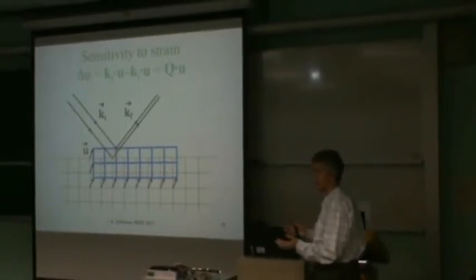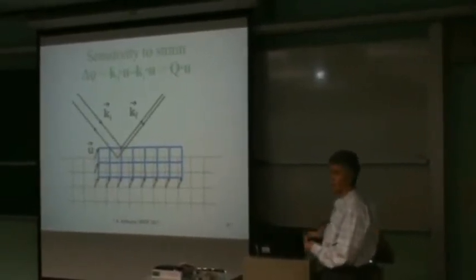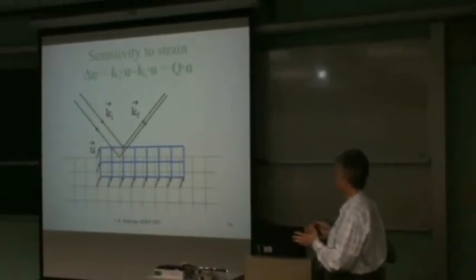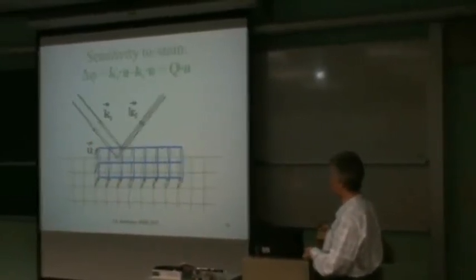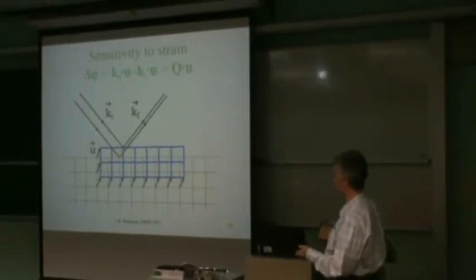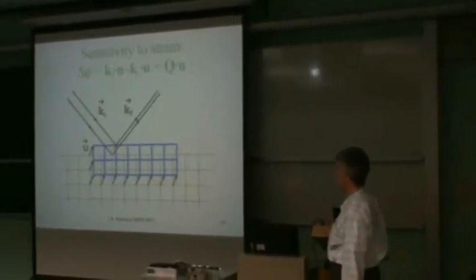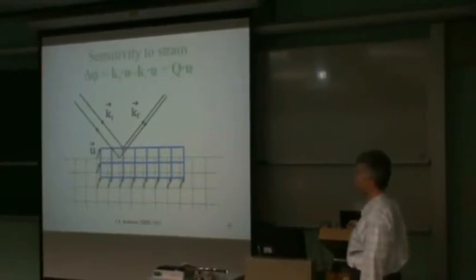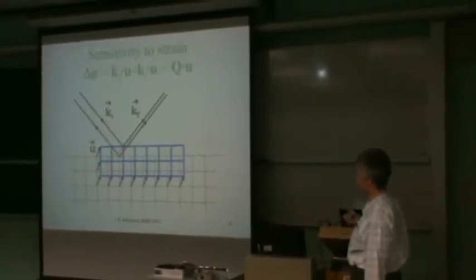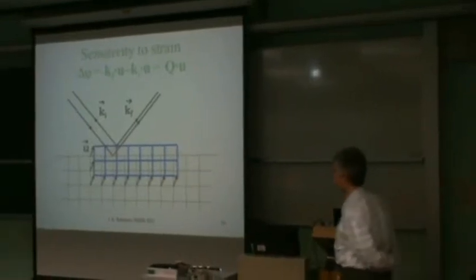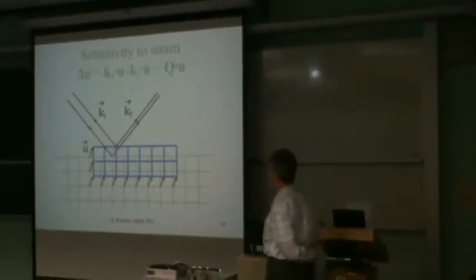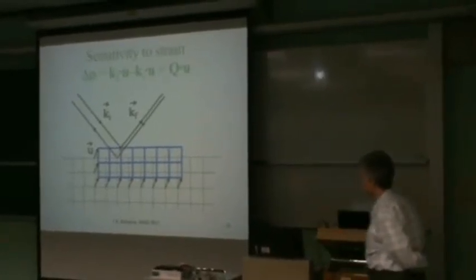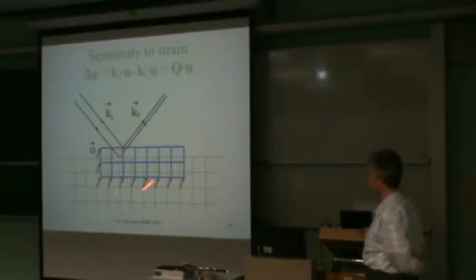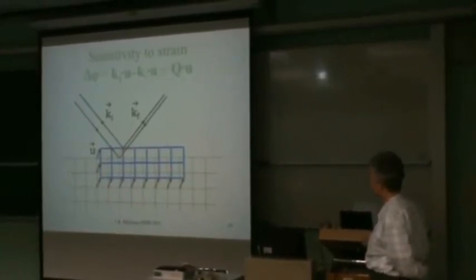Whereas the image has a resolution of about 20 nanometers or so typically, the phase has extremely high sensitivity to the distortions in the crystal, because as you can see from this picture, if you move the crystal by a whole unit cell, it's indistinguishable from the undistorted one, and you get a phase of 2 pi. So your range of phase from 0 to 2 pi for the image corresponds to 1 unit cell of displacement of the material, and a unit cell is a fraction of a nanometer. So it's really quite sensitive. You can get measurements of distortions down in the picometer range by this method.